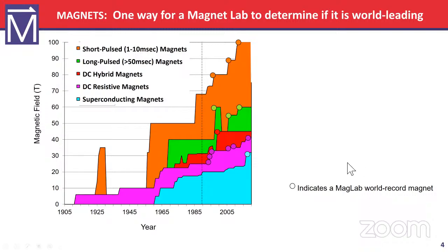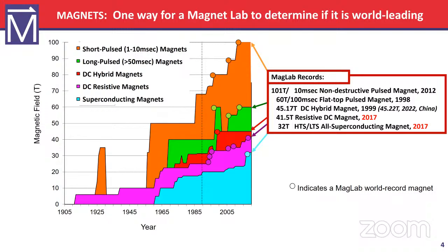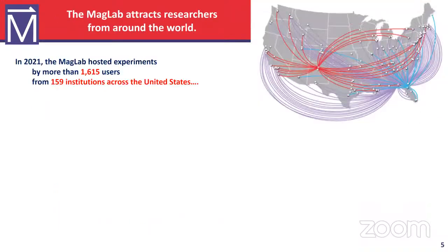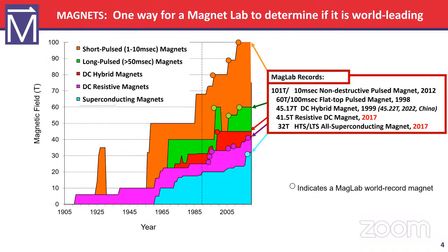Okay. And so the current world record, 101 Tesla, 60 Tesla for longer pulse magnets. We got 45.17 Tesla, the Chinese, in 1999. The Chinese just 2 weeks ago announced 45.22 Tesla. We're recording, okay, so I'll wrap that up. Not yet. The resistive magnets, we get to 41.5, and we build a 32 Tesla all superconducting magnet, which is the highest superconducting magnetic field in the world.